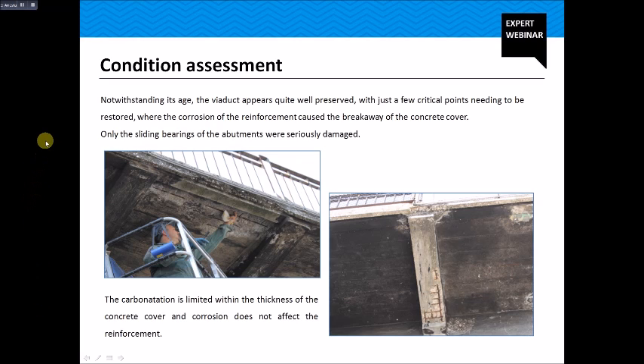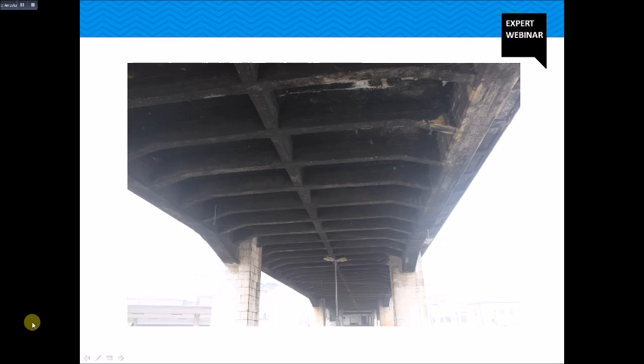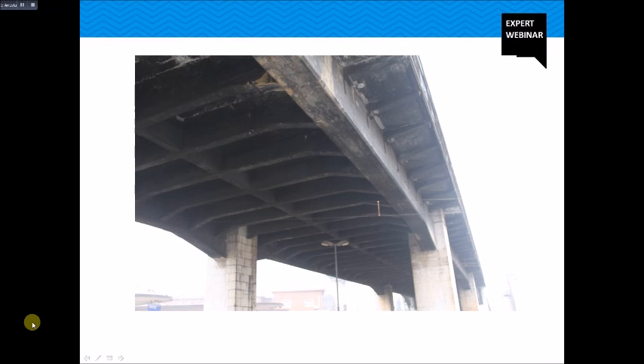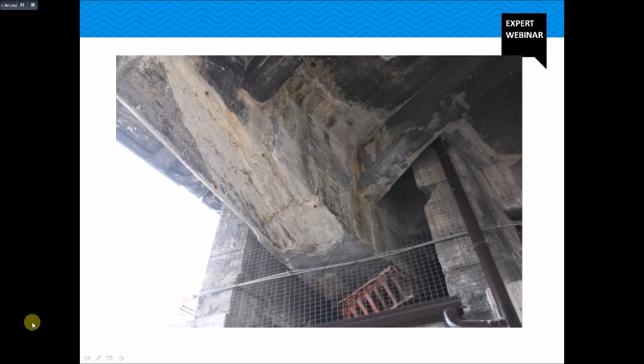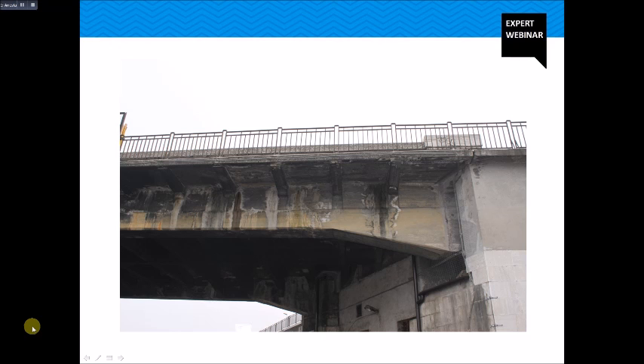Notwithstanding its age, the viaduct appears quite well preserved, with just a few critical points needing to be restored, where the corrosion of the reinforcement caused the breakaway of the concrete cover. Only the sliding bearings of the abutment were seriously damaged. The carbonation is limited within the thickness of the concrete cover, and corrosion didn't affect the reinforcement. As you can see in these photos, concrete is not damaged and only superficial treatments are required. The thick coating of black grease smoke layered by the ancient steam locomotives probably protected the concrete surface from aggressive agents.